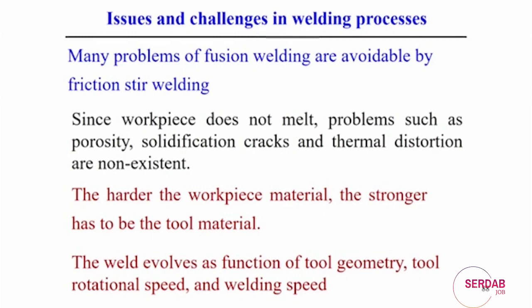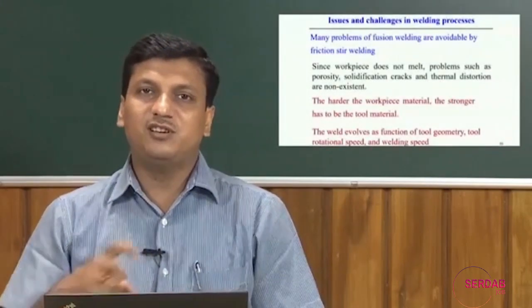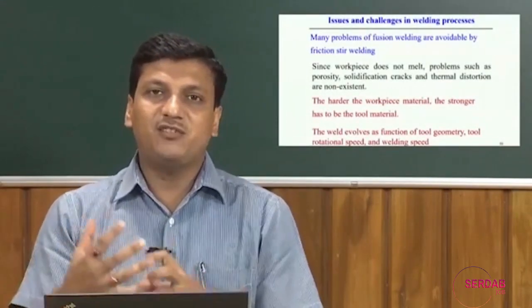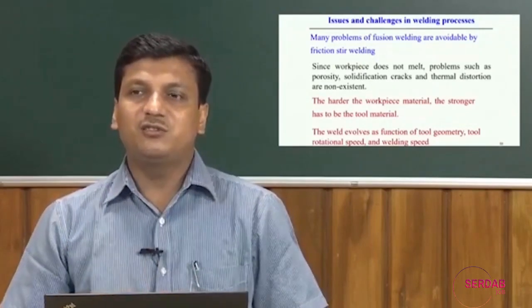But the only difficulty is that a limitation of the friction stir welding process is that if there is insufficient material flow, it can create some defects. But in general, the harder the workpiece material, the stronger the tool material required. And because the weld evolves simply as a function of the geometry of the tool, the tool rotational speed and the welding speed, these actually impact the final weld joint quality in the solid state welding process.